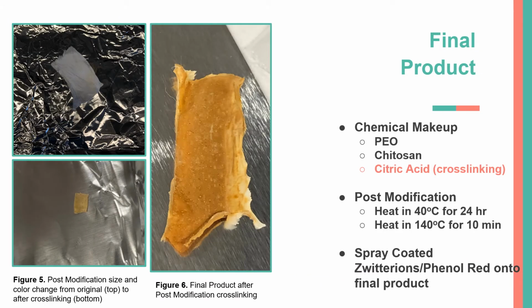In order to address these mechanical issues, for our final product, we swapped out acetic acid for citric acid. This allowed us to cross-link our material through post-modification. Our electrospun mat was dehydrated for 24 hours at 40 degrees Celsius and then cross-linked for 10 minutes at 140 degrees Celsius. Additionally, Zwitter ions and phenol red were both attached to nanoparticles and sprayed onto the mat after cross-linking. This was done so that the particles would not be damaged by the heat, and will be further discussed in the section focusing on nanoparticle incorporation. In Figure 5, it is plain to see that the mat shrinks in size throughout post-modification and becomes a darker brown.